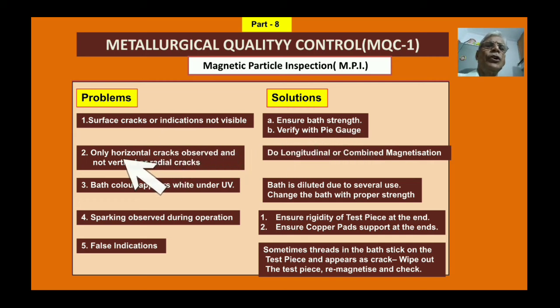Then point two is that only horizontal cracks are observed and not vertical or radial cracks. This depends upon what type of magnetization you are doing. Do longitudinal or combined magnetization, because if you are doing circular magnetization, you can see only horizontal cracks. You cannot see vertical cracks. So this has to be taken care of, whether you are doing longitudinal or even combined magnetization, which can reveal both circular as well as longitudinal cracks, and sometimes radial cracks also. This is the advantage of doing combined magnetization.